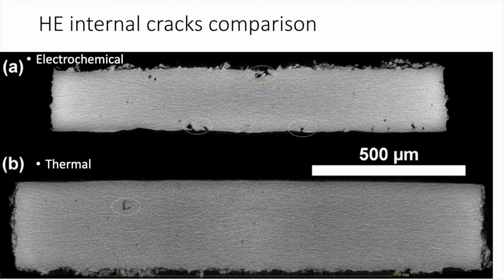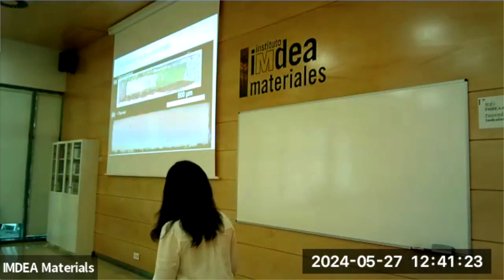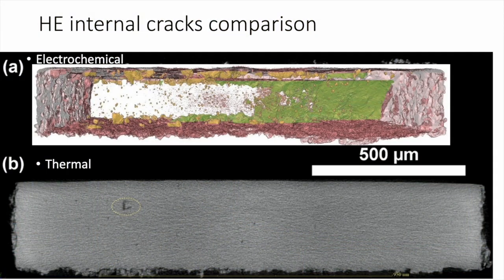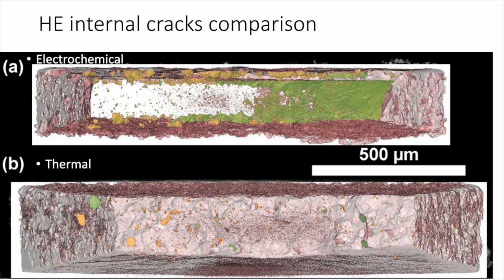To give a better illustration, we extracted the cracks and the pores inside the material by taking the grayscale value of each of the voxels. As you see here, the yellow and green ones are marked with different colors because of their size. The yellow and green ones are the cracks and the pores. This is the electrochemically charged one, and this is the thermally charged one. So you see, in the electrochemically charged one, we got a giant crack, and there are many cracks on the surface. Well, for the thermally charged one, we see cracks mostly in the middle.